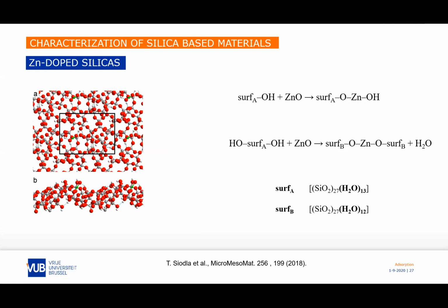So then after these group 6 elements, we also checked some other elements. The idea is, once you have this model, we can try to insert or graft the whole collection of transition metals, because they have all found applications in heterogeneous catalysis. And one of the topics chosen together with experimentalists was zinc oxide. So here again, we have zinc oxide, which is much more limited in the number of grafting possibilities, because we have a much lower degree of oxidation. So we have mainly a coordination of 2 direct chemical links.